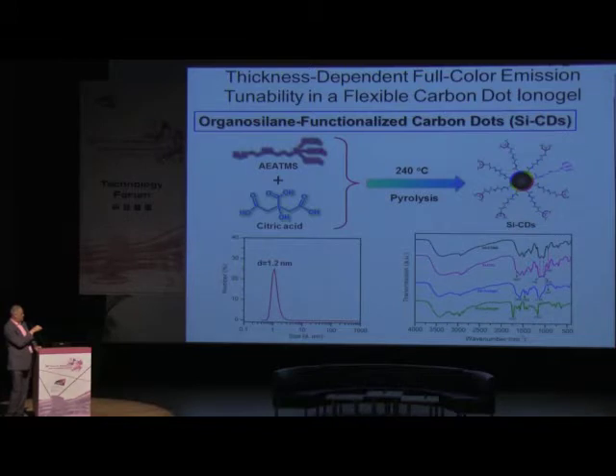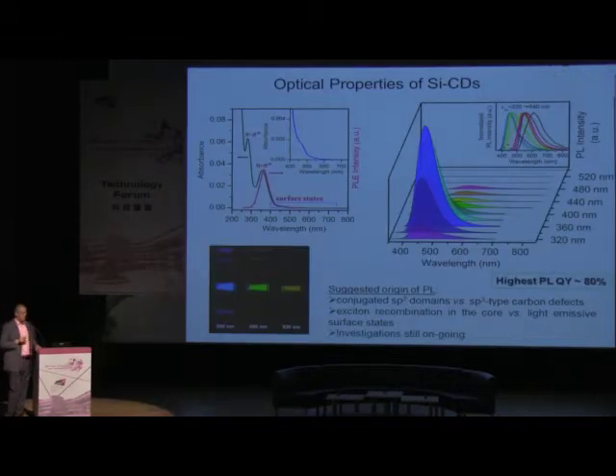They're tiny, like 1.2 nanometer diameter. They show all these characteristic peaks in FTIR spectra, which tells us that they indeed look like here. They have a graphite-like core and silanized surface. And optical properties of carbon dots are quite different, in fact, from the optical properties of semiconductor quantum dots, because their emission is not so much size dependent, but excitation wavelength dependent.